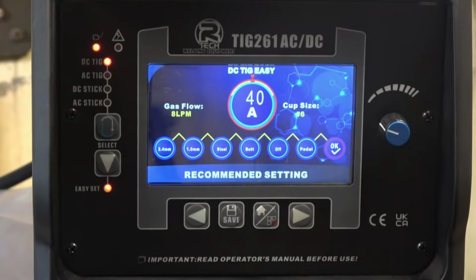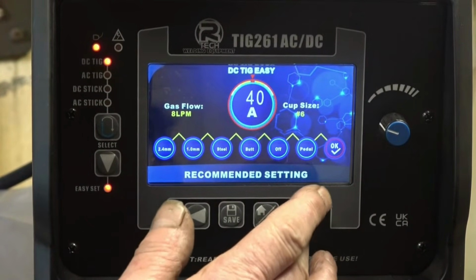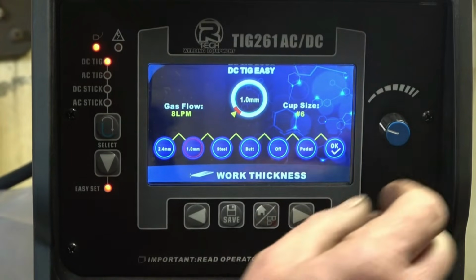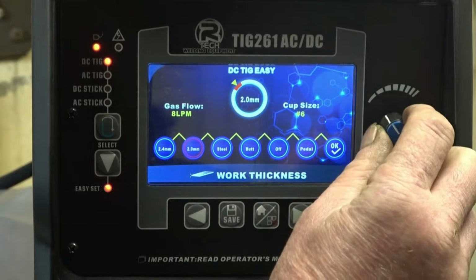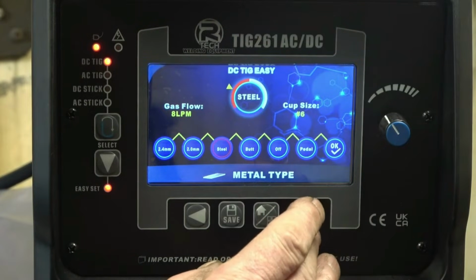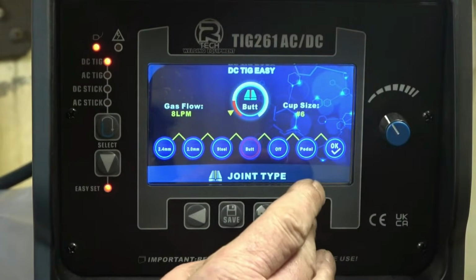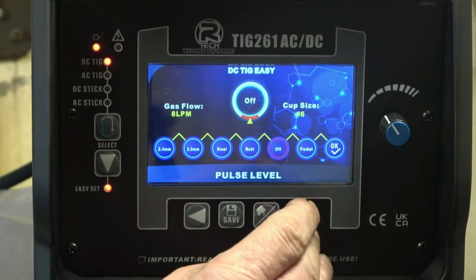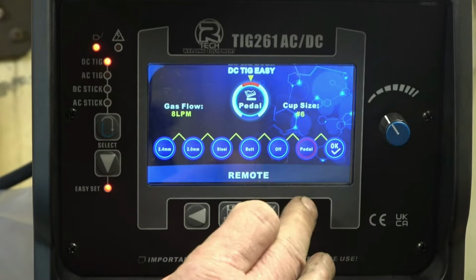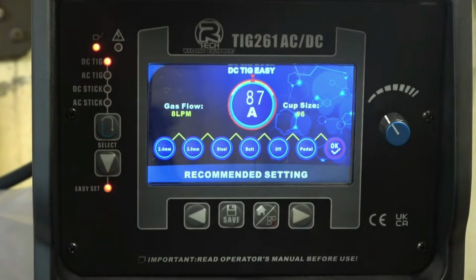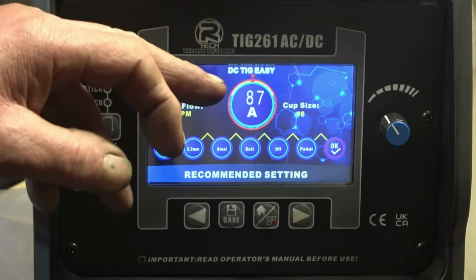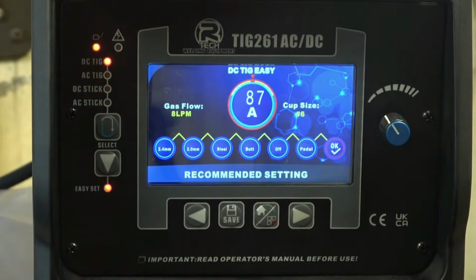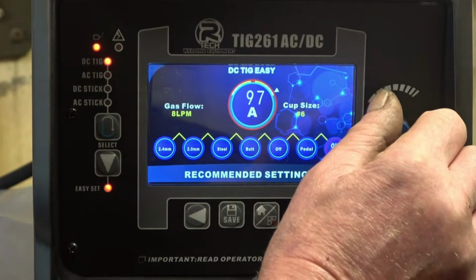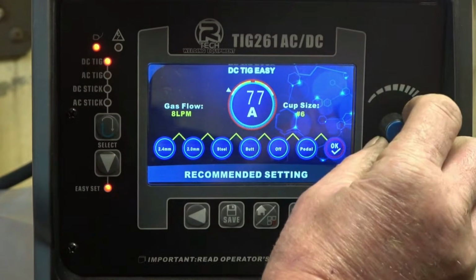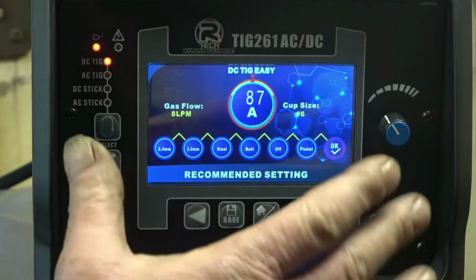I'm going to move up to 2mm now, so we're in Easy Set. Same tungsten 2.4, work thickness 1.2, 1.5, 2mm, on an ordinary steel, steel or stainless. I'm going to do a butt joint again. The pulse is off, and I'm going to use a pedal. OK. So now it's going to give us the same 8 litres a minute, 87 amps. Cup size 6. If you're welding and you find the weld's too cold, you've got a 10 amp adjustment to go up, or if it's too hot, you can go down 10 amps. So you've got a 20 amp window to finally tune it in just the way you want it.